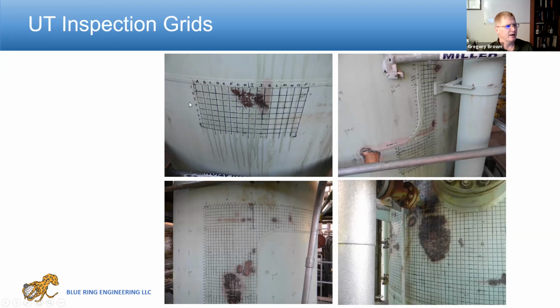So grid 1, you can see, is not too bad. There are some bands of corrosion near this circumferential weld. We also have some patches of corrosion located at the edges of this patch plate, as you can see. You can see the grid over on the side where they took some thickness measurements. Note on this vessel, you can see in the pictures external corrosion. There was also internal corrosion we had to account for as well. In the lower left, you can see the patches of corrosion around the patch plate. And then finally, over here on the lower right, what you're seeing is patches of corrosion in the second shell course near these nozzles. So grid 1, as you see here, passed a level 2 assessment. This is good to stay in service.